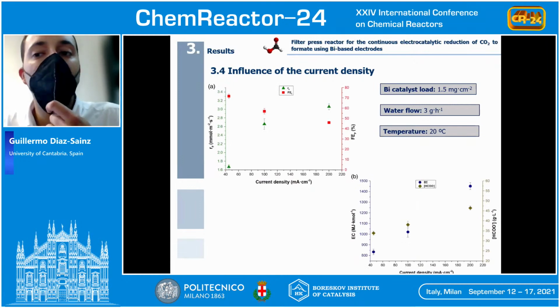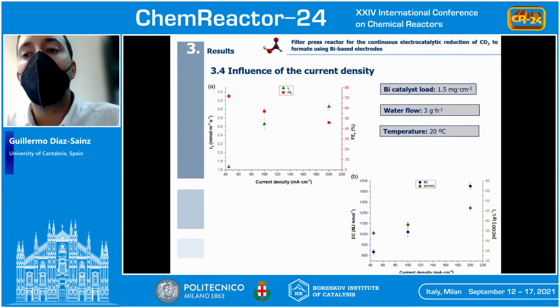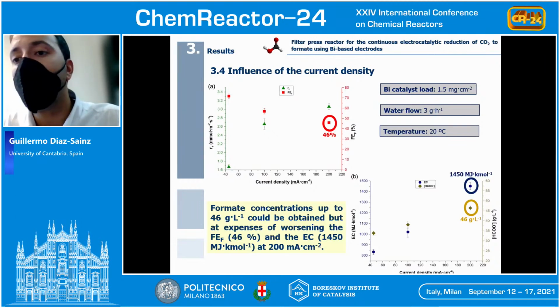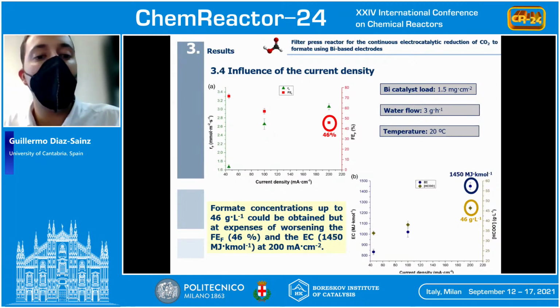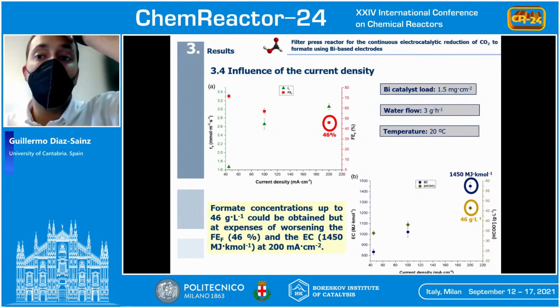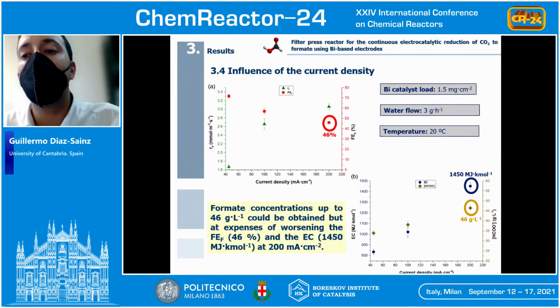And finally, the influence of the current density. In this section, all experiments were carried out with the bismuth catalyst loading, water flow, and temperature that are considered optimal in the previous sections. We can observe that increasing the current density from 45 to 200 milliampere per square centimeter, the formate concentration increases to values of up to 46 grams per liter, but at the expense of decreasing all the other figures of merit, that is the Faraday efficiency, and increasing the energy consumption, achieving values of 1,450 megajoule per kilomole.